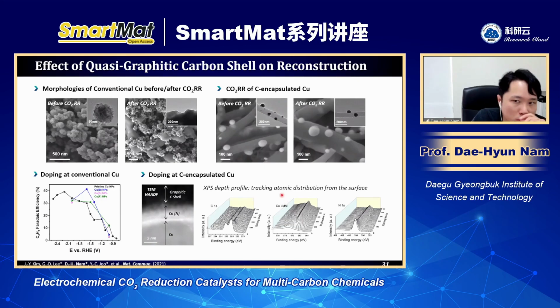The interesting point is that this carbon not only protects the copper active site, but also enables the penetration of ions. It means that although we have the carbon shell, when we did the doping with boron and nitrogen, we found this nitrogen can penetrate the carbon shell, and this can dope the copper inside. So there is a reason why our carbon shell is very effective for the CO2R and for preventing the reconstruction together.